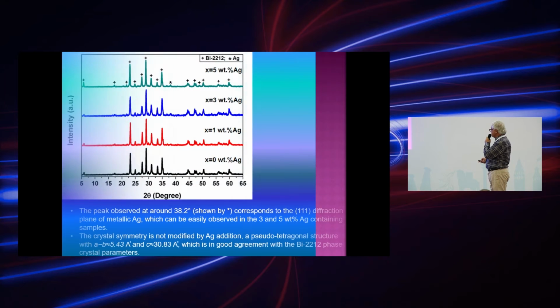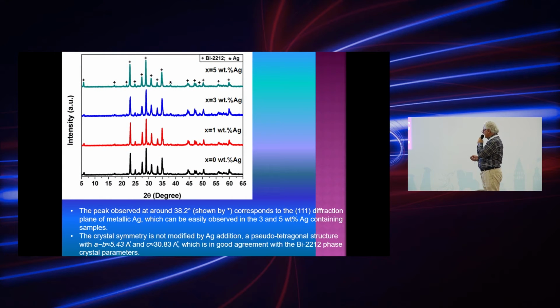Now let me come to the results. Firstly, we have measured their XRD, and I would like to show this part. This peak around 36 is related to one diffraction plane of metallic silver. When we look at this part, it increases with increasing silver content. The others are almost pure 2212 phases. We have calculated the crystal parameters: A and B are 5.43 angstrom, and C is 30.83 angstrom, which is in good agreement with the normal 2212 phase given in the literature.